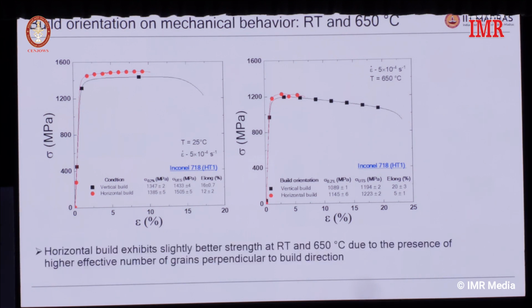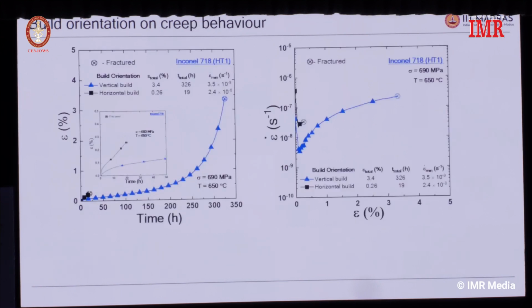So possibly because you have a higher number of grains along the horizontal direction, that's why you get a better strength. But if you look at the creep properties, the horizontal build and the vertical build, what you see here is that the horizontal build doesn't give the better creep rupture life. In fact, the creep ductility is very low. You can see that from the plots here of strain rate versus strain.